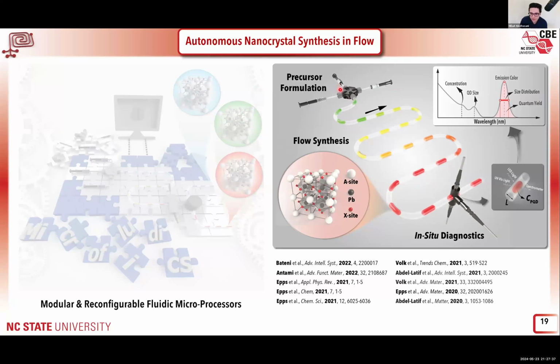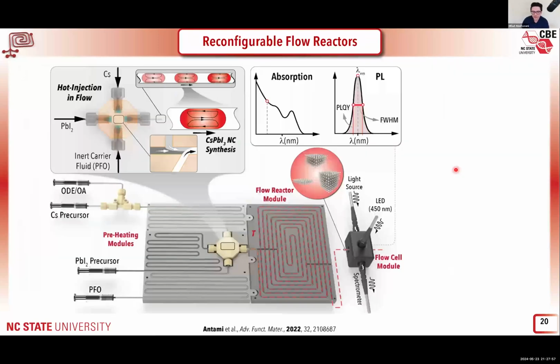We can then have different temperatures, different reaction times. At the end, we do in situ or online characterization for material synthesis. We do in situ spectroscopy. We're using the same spectrometer, but with two different light sources. We can do in situ UV, near-infrared spectroscopy, or photoluminescence spectroscopy. And then having selective heating of the precursors is extremely important so that you can have access to different synthetic routes of these semiconductor nanocrystals.